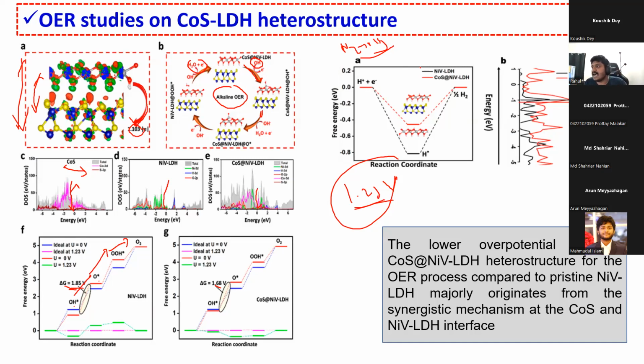It's hydrogen evolution, right? As I showed previously, you see this kind of plot in the nitrogen reduction reaction. A similar kind of plot you can see here. For the pristine nickel vanadium LDH, the value is very far from the thermoneutral value. But after making the heterostructure, this value reduced, and it's closer to the thermoneutral value. That indicates that it has a very good HER characteristic. How do we actually examine why it's showing very good HER property?